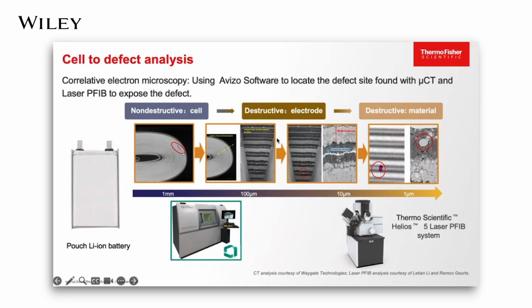If you see this image, we will find that this site is several cathode and anode electrode layers, millimeters deep from the surface. We achieve the cross-section with the femtosecond laser that is available on our DualBeam tools. We call it the tri beam, which allows us to expose really deep features like shown here. Finally, we found the cathode material present in the anode electrode.